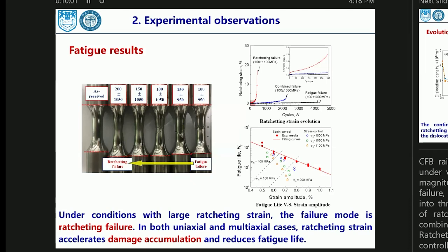Under the conditions with a large ratcheting strain, the failure mode is the ratcheting failure mode, and in both the uniaxial and some multi-axial cases, ratcheting strain accelerates damage accumulation and reduces fatigue life.